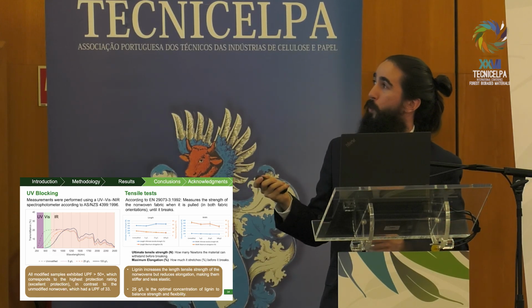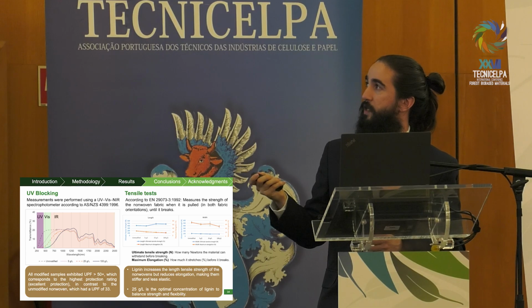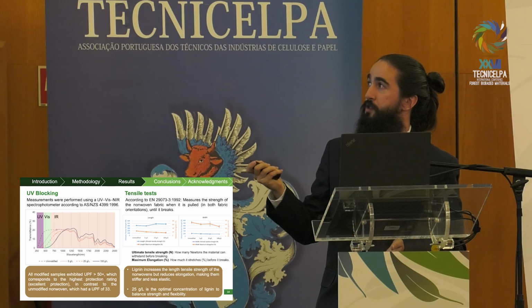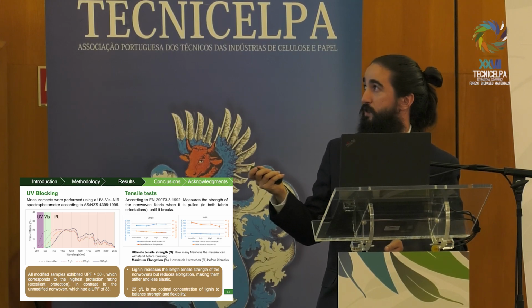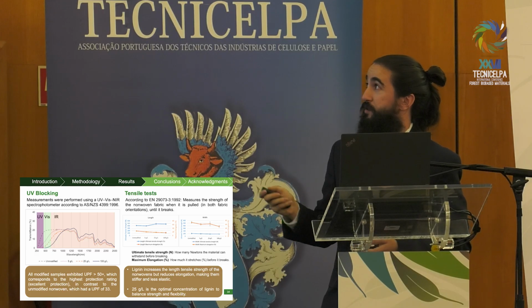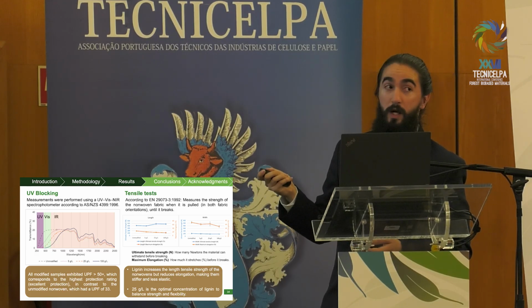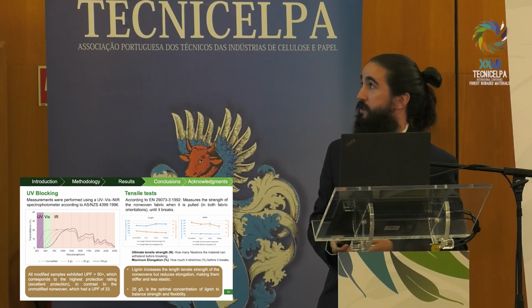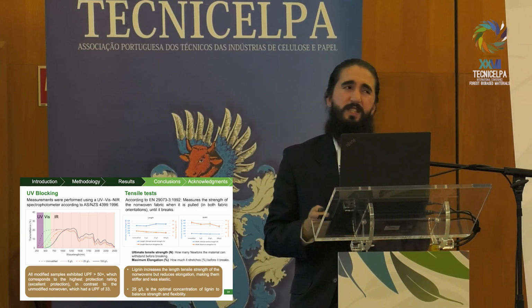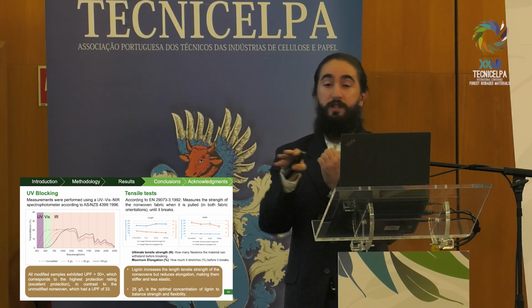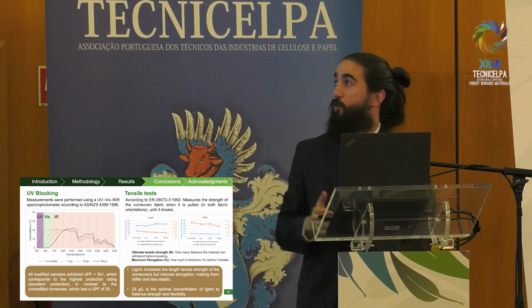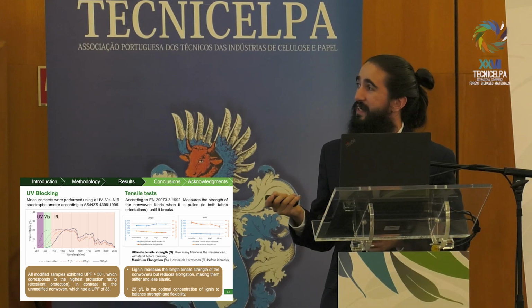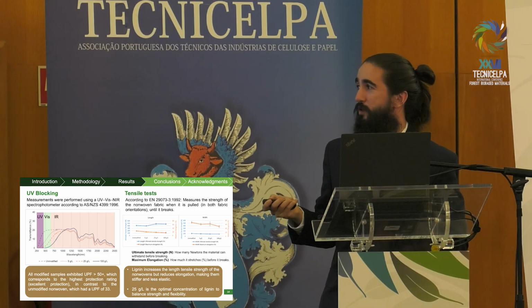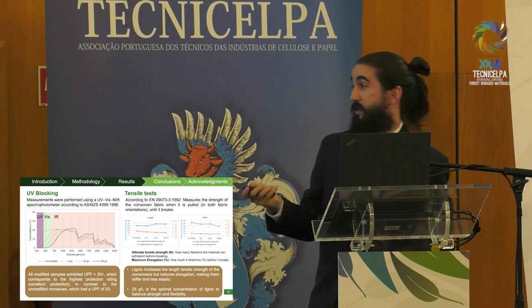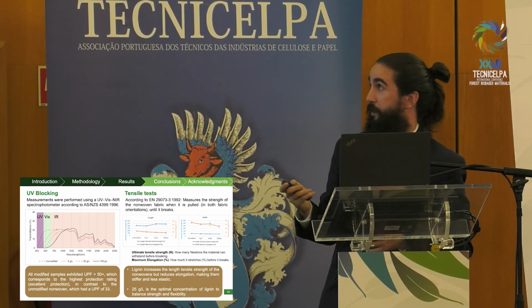And as you can see here, when we add only 5 grams per liter, the ultimate tensile strength remains basically the same at 400, but when we add the intermediate concentration, it jumps to almost 500 newtons, although the maximum elongation is constantly decreasing. On the width direction, the ultimate tensile strength is much lower, around 100, but the elongation also sharply decreases. So we have an anisotropic behavior, which is typical of nonwovens, because they are stronger in their machine direction, and of course with the hot pressing, we also contribute to this phenomenon. So we can say that lignin makes our samples a little bit stiffer, but also less elastic. And once again, the intermediate concentration seems to be the ideal point.